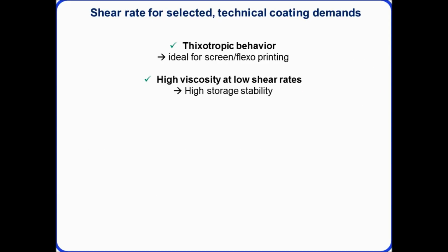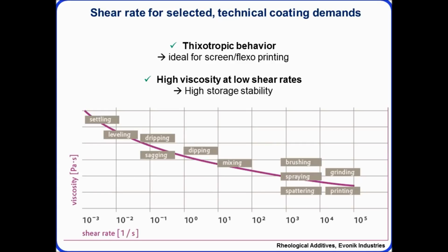So the ideal behavior for an ink, especially for screen and flexo printing, is to have thixotropic behavior. This is where, as we apply some shear to the material, it will start to thin, so you have a shear thinning behavior. And once you stop printing and you stop applying shear, the viscosity should rebuild, and you can therefore have a defined feature size. So ideally we want high viscosity at low shear rates. Again, this helps us to stabilize the material, the ink.